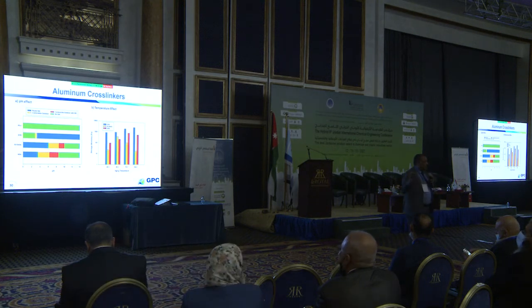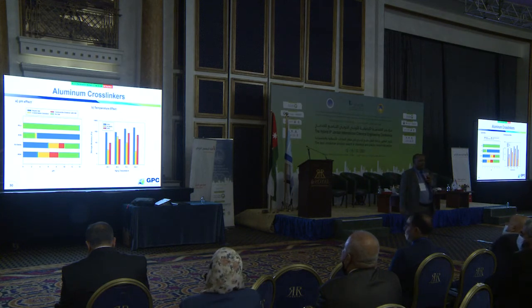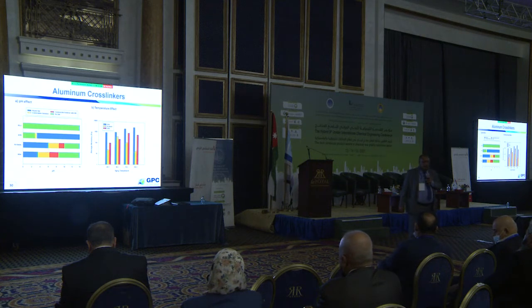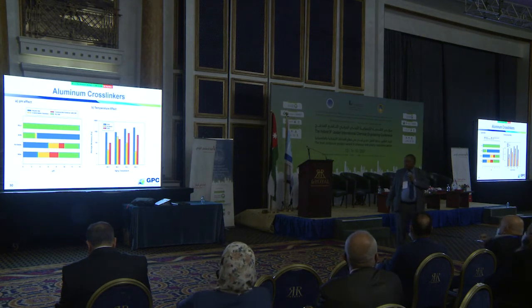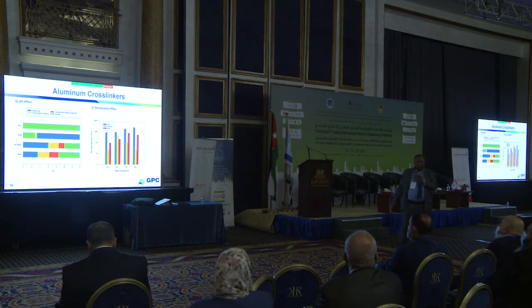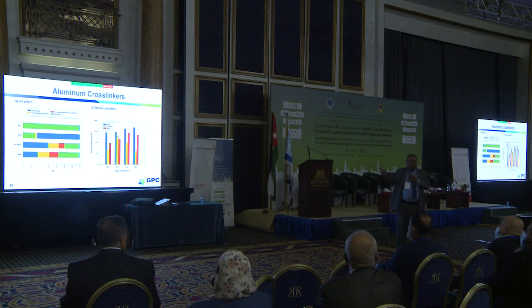Later on, another important contribution that we made is that we worked a lot on cross-linkers, especially inorganic cross-linkers. We developed this cross-linker, aluminum acetate. We studied different types of aluminum. We moved from chromium to aluminum because it's more environment friendly, especially if you want to use it for offshore. And we found aluminum acetate is the best. You can play with pH and get different strength.